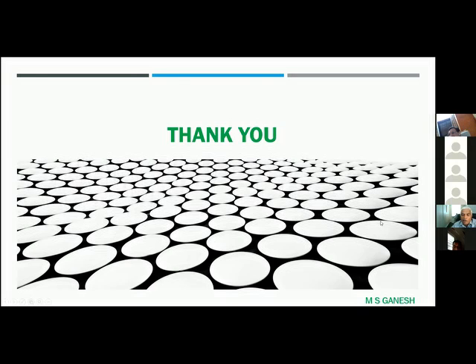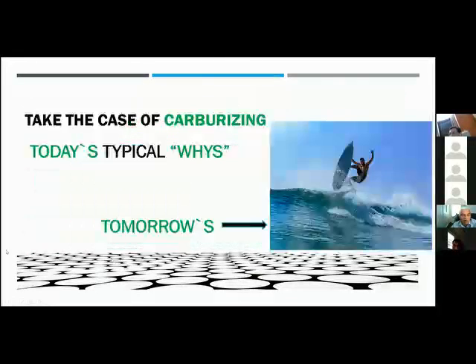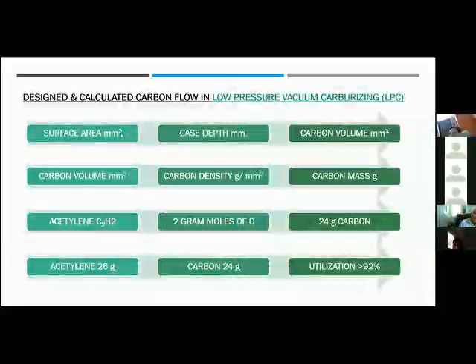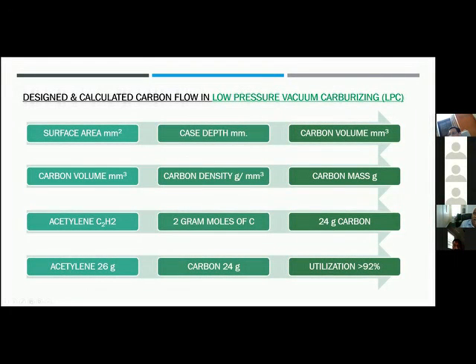And if I can quickly go back, what we do, as I told you, is we calculate for every geometry of the component that you have in a batch. You calculate the surface area, you know the case depth, you calculate the carbon volume, look at the density, get the carbon mass, know its acetylene. So we find out the mass flow of the acetylene. Now I'll come to this part which I have not shown.